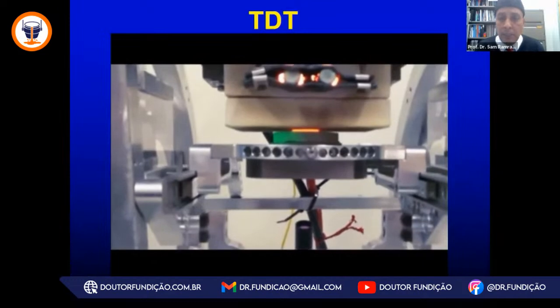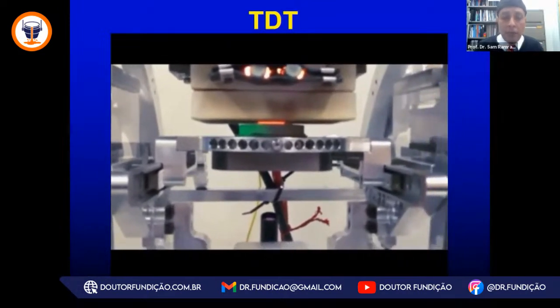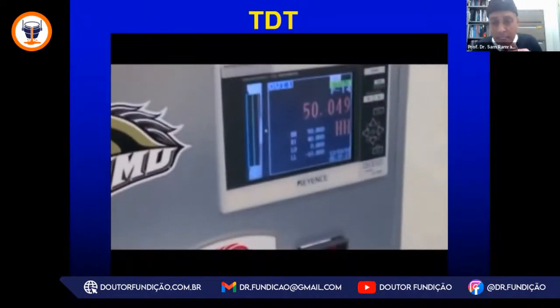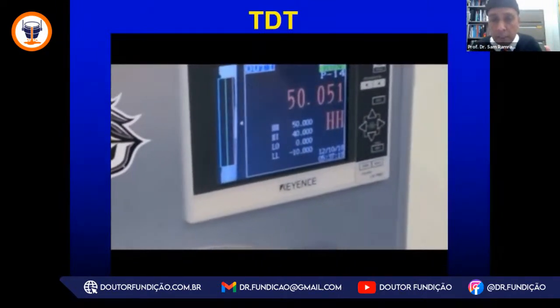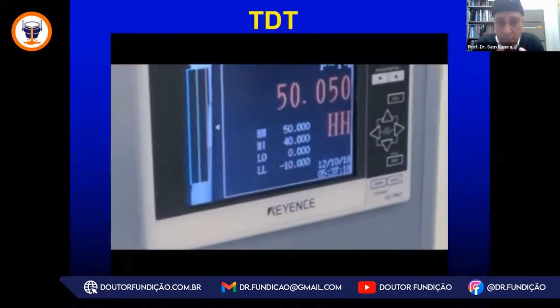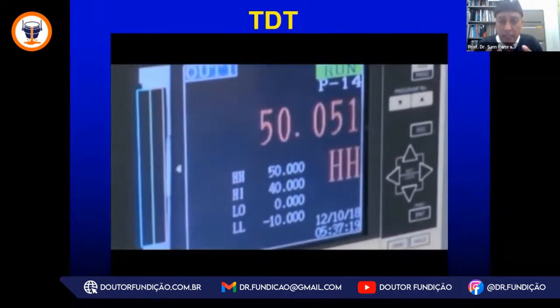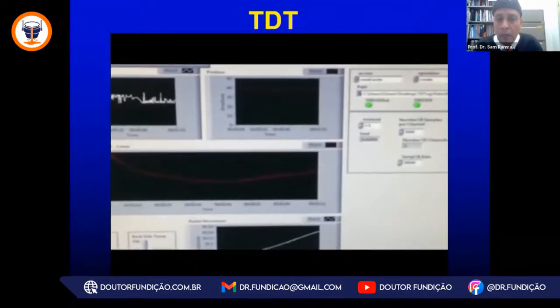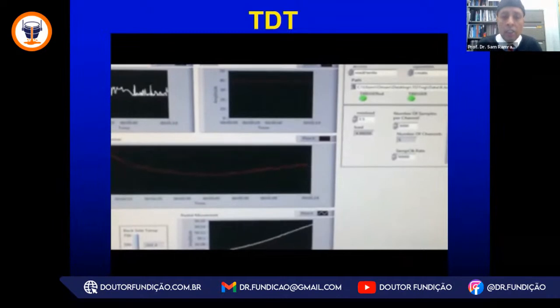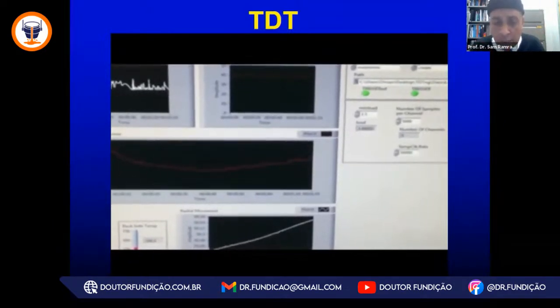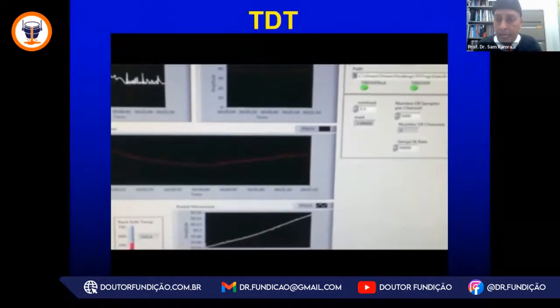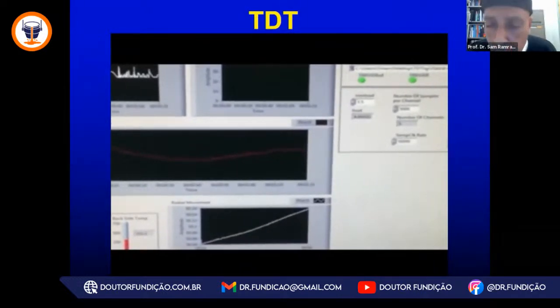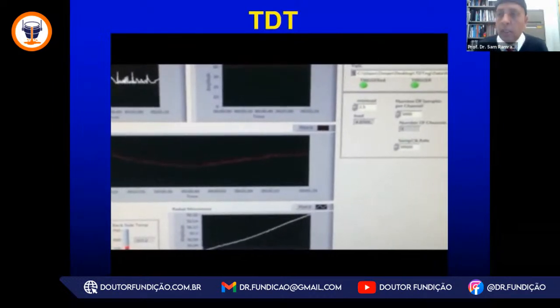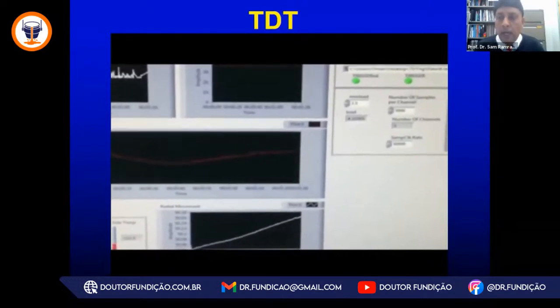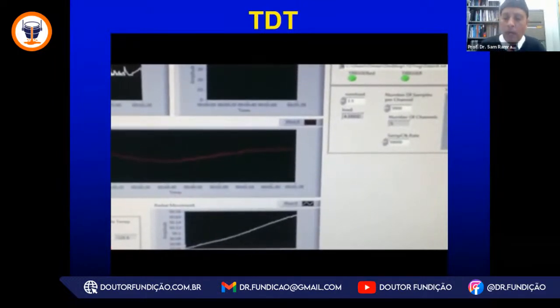It brings the specimen against a hot surface. We are measuring temperature on the backside and at the hot surface, so we can measure a thermal gradient. And you will see that the specimen that is 50 millimeters in diameter is radially expanding in real time. We measure the radial, the axial changes, and the heat transfer in this system in real time. That data is acquired so that we could develop the thermal distortion curves for the test for further analysis after the test has been completed.